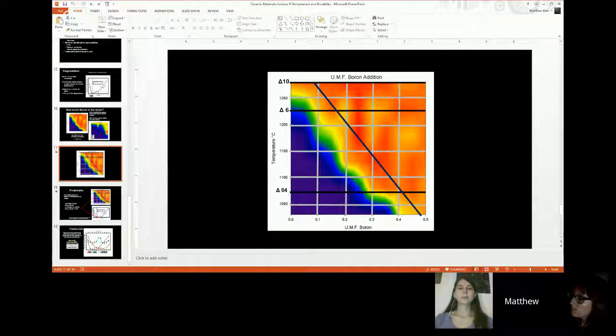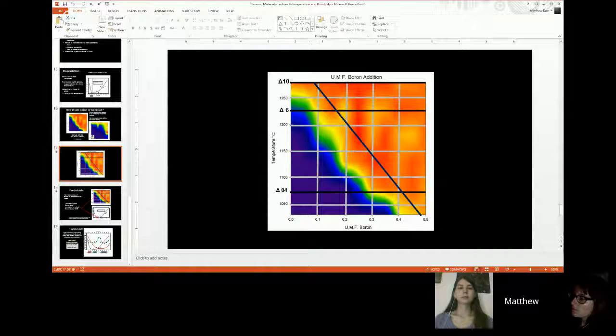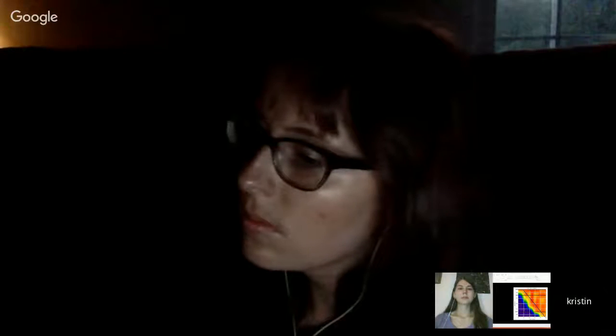And so those are attacking your glazes. If your glazes have too much alkali metal, lithium, sodium, or potassium, they become chemically susceptible to this ion exchange. So what I found at cone 04 is that as long as you keep your flux ratio within the 0.3 to 0.7 ratio, the glaze is exceptionally durable.